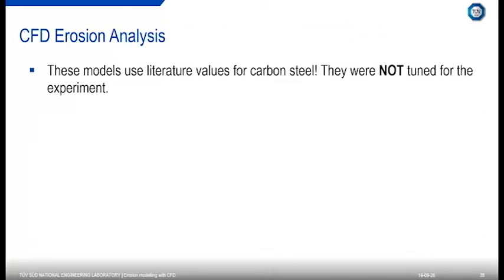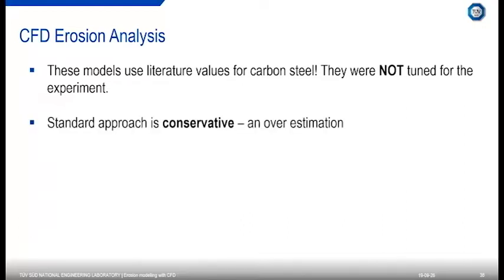So what I will say is the values that I used there were for carbon steel, and I didn't actually tune them for the experiment. I didn't have coupons. These are based on literature values. Sometimes literature values are fine, but you do need to validate and compare that. The standard approach is good, but it's conservative, and I suppose that's what you want when you're trying to do some analysis here. So we had a peak of 1.4 millimeters compared to a peak of 0.8 against the experiment.